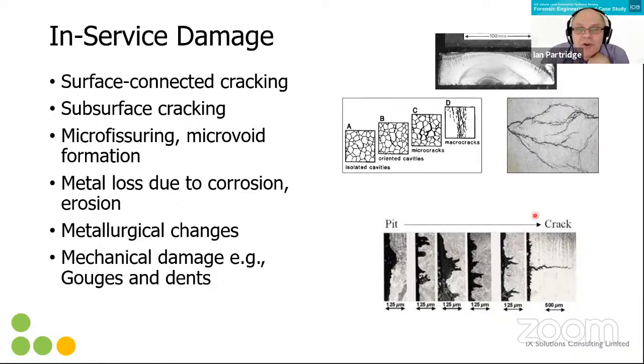What you get over time, you're getting the grain boundaries of the material, microvoids occurring. You get initially isolated cavities. Then these cavities start orientating towards a perpendicular stress direction. These cavities then link together, become a micro crack, and then they become a macro crack. So you're seeing this here. In creep, if you see any cracks, that's the end of life. Even very small ones.